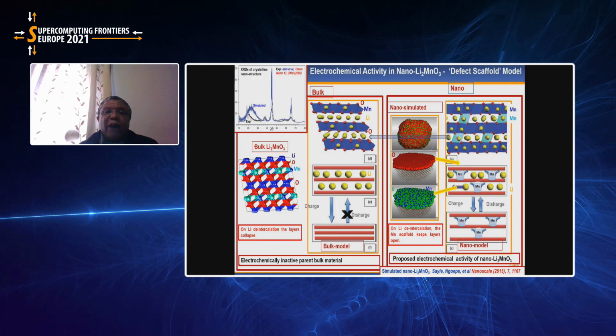We found that in the structure of the Li2MnO3, we have what we call the oxygen layer, and a layer consisting of manganese and lithium. Lithium is in yellow, and there are some layers consisting of only lithium. When you charge the material, you take the lithium out of the system, and when you have these layers which consist of lithium only, the system ultimately collapses. And when you discharge, they can open up, and then the system becomes electrochemically inactive.